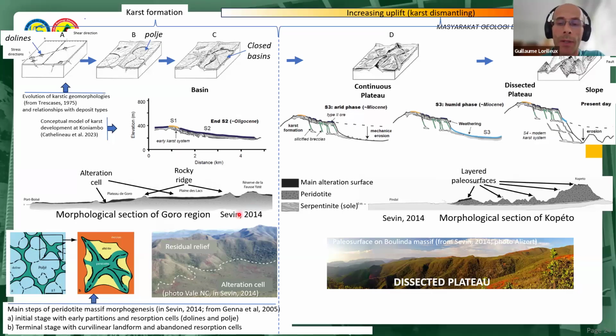So this is a typical karstic landscape with dolines and underground channels, and this corresponds to the initial morphology of all the peridotite before uplift. With more uplift, basins become plateaus by topographic inversion. As uplift increases, the karst topography is dismantled due to erosion by rivers, the laterite becomes dissected, and slope systems develop in relation with gravity-driven faults.